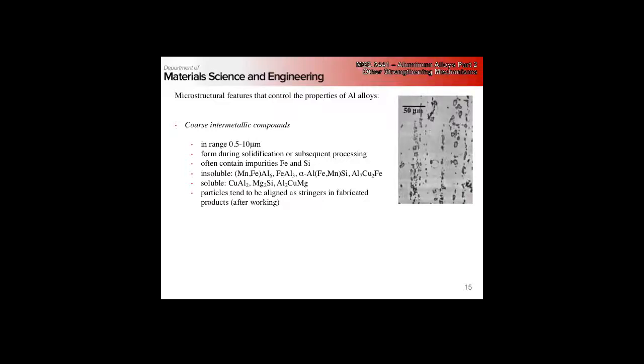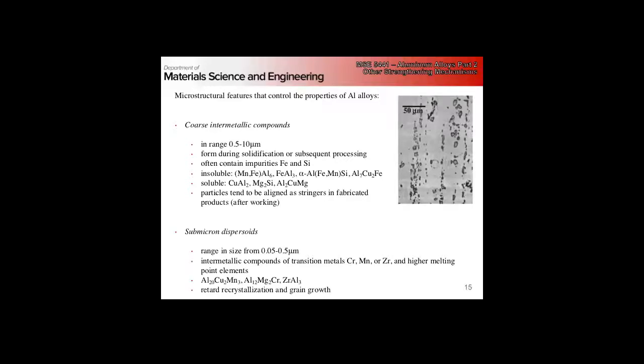During deformation, if we have particles at grain boundaries and equiaxed grains that we then pancake out, we end up with long stringers of these particles, and we can generally break them into two classes: insoluble, which don't have a clear solvus on our phase diagram, and we have to take them up to the liquid to dissolve them, and soluble, which will dissolve back into the matrix at elevated temperatures in the solid state. So that's the first microstructural feature we want to consider.